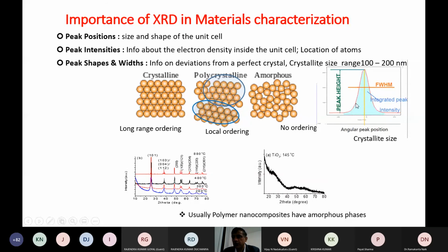If it is really nano, we can see more broadening. It clearly indicates that your materials are really nano. So this is one way. This technique is very useful to do before doing the expensive TEM technique. I think with a simple XRD, you can check whether this material is, for example, nano size or not.